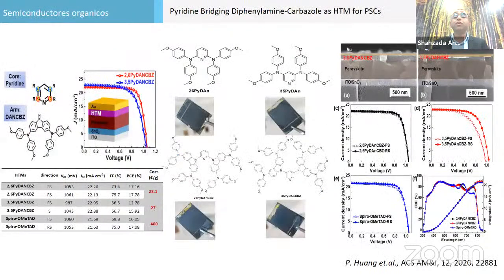This is just one example of pyridine-bridged diphenylamine-carbazole. Carbazole is a very good organic semiconductor material with good mobility. With pyridine, they will passivate the perovskite surface. With only pyridine, the thin film was not uniform. When you add carbazole, the electrical properties improve, and the uniformity of the deposited film also increases.